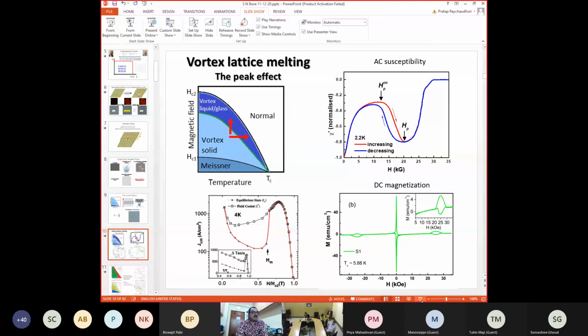So the phase diagram, when you include this complication, is a little bit more complex. You have this Meissner state here, but then this region, which is the mixed state, actually has a region here where you have a vortex solid, but then when you increase temperature, you can melt into a liquid, or as you will see later, a glass. And if you also increase magnetic field, you can melt into a liquid or a glass. So you have this additional line that separates this mixed state into vortex solid and vortex liquid.